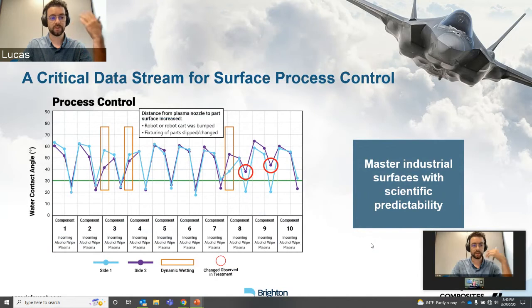And what you can see, just quickly scanning left to right, is our incoming material in general is right around 60 degrees. The IPA wipe brings it down about 5 to 10 degrees, okay? And the plasma, on average, gets us to the mid-20s. But there's a couple interesting things here. Component number 3 and component number 4, the incoming material was super different. It had dynamic wetting all over these cast aluminum parts. The rinse process that they were using had gone to heck, and it wasn't working anymore. But our alcohol wipe returns us back to the 50s, and our plasma gets us back down to the mid-20s. Our process handled that incoming variability without an issue.